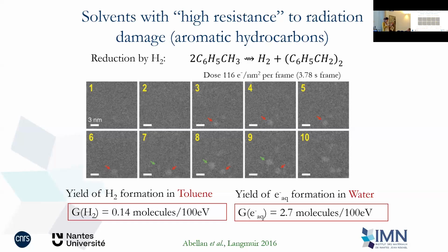I did a figure where I was comparing directly the data from the synchrotron with what we did in the electron microscope, because I said, you see, the redox potential is similar. And a reviewer came back and said, you cannot possibly be serious doing this comparison with the microscope. But yes, the dose rates are different, but your reducing agent has similar properties when it comes to reduction, because it's a similar redox potential.